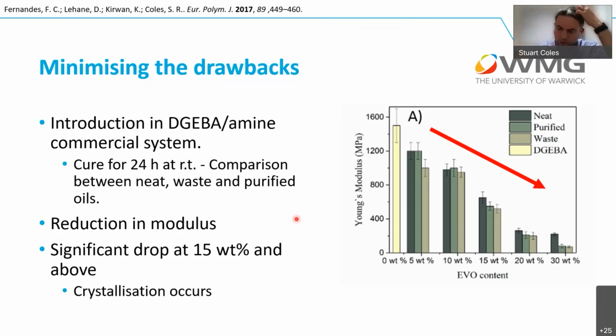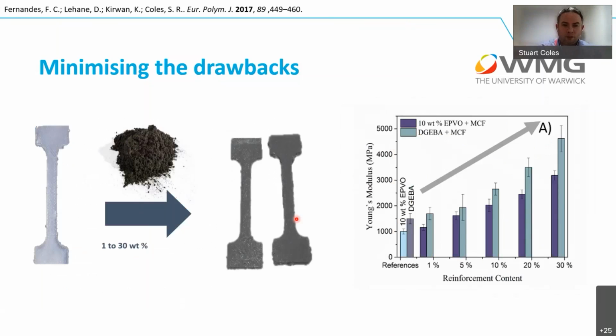So one of the things that we then thought of was, can we put a very simple additive in that at least returns us to the properties that we once had? One of the things that we looked at was this product here, which is effectively a milled carbon fiber. That's a reclaimed carbon fiber that's effectively a powder product, which can be used as quite a cheap, sustainable filler. It doesn't have anywhere near the environmental impact of virgin carbon fiber, because it's effectively reclaimed waste material that we're then doing something with. We did that from 1 all the way through to 30% of carbon fiber, with the standard DGEBA system and our 10% epoxidized waste oil. And we can see again that as we add carbon fiber in a composite structure, we get an increase. Now, we don't ever reach the same levels of DGEBA.